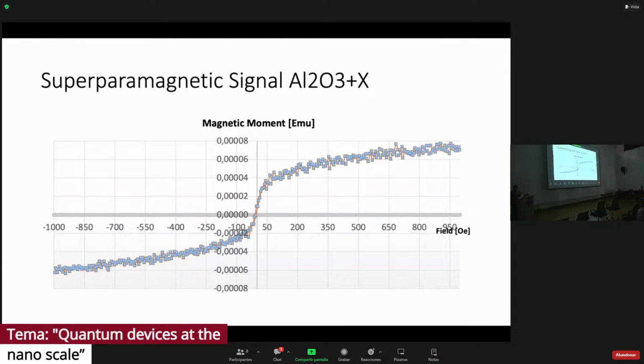We do that. Remember that we change temperature. In this case, we start applying magnetic field, and then we see a clear dependence of the IV characteristic on magnetic field, which is a very good result. We were very happy. We're still analyzing this data. I just can tell you what happened.